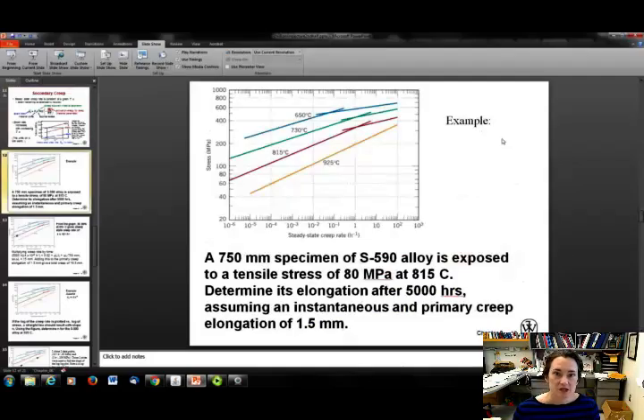Okay, so let me do an example problem for you so that you can see what some of these creep problems look like. I actually have about 3 examples here to go through. So this is a steel alloy, S590 alloy, and it's 750 millimeters long initially, and it's exposed to a tensile stress of 80 megapascals at 815 degrees Celsius. And so using these plots, what we're going to do is determine the elongation after 5,000 hours, assuming that the instantaneous and primary creep elongation is 1.5 millimeters.